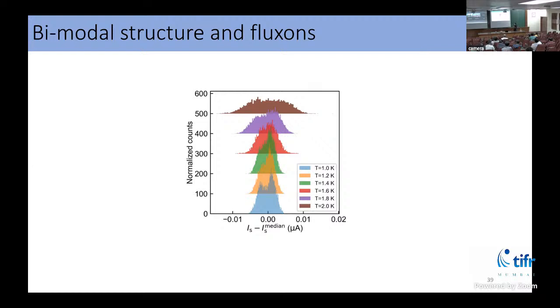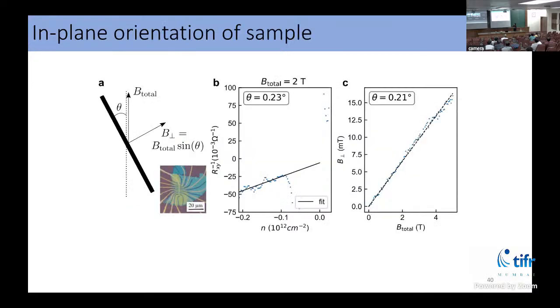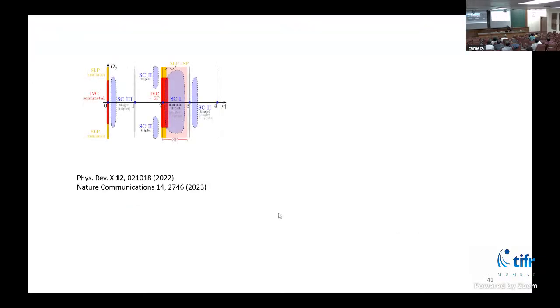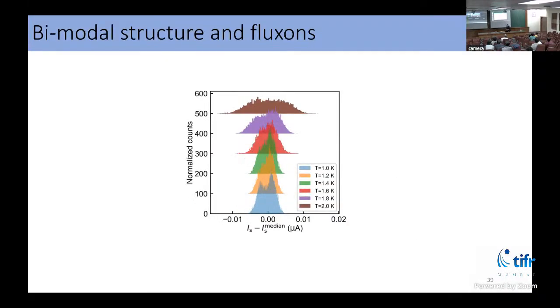And why that is, because remember this particle in a potential picture that I was telling you about. Whenever you are tilting this potential, when I am at zero current, this potential picture is flat. There is less probability of that particle going out of the potential. But as I have tilted, there is increasing probability of that particle popping out. So at higher currents, actually, you will see that it is sort of more, but it has a long tail at lower currents.